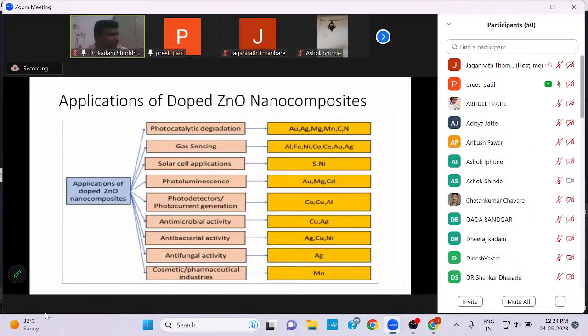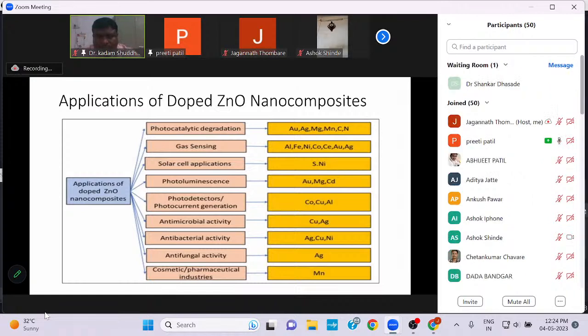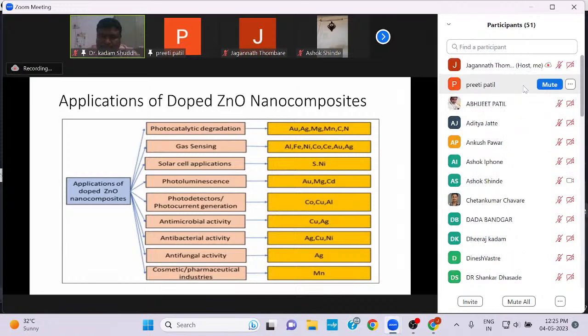Aluminium doped ZnO thin films show high response and recovery towards ethanol gas sensing. Similarly, iron, nickel, cobalt, copper, gold, and silver also show different gas sensing activities. If you come to the antimicrobial or antibacterial activity, the reactive species produced by photocatalytic degradation can be used as an antibacterial agent that can rupture the outer membrane of the bacteria, inhibiting the growth. Doped ZnO is categorized as the most promising inorganic antibacterial agent that is more stable and safe and can be used in the absence of ultraviolet light.